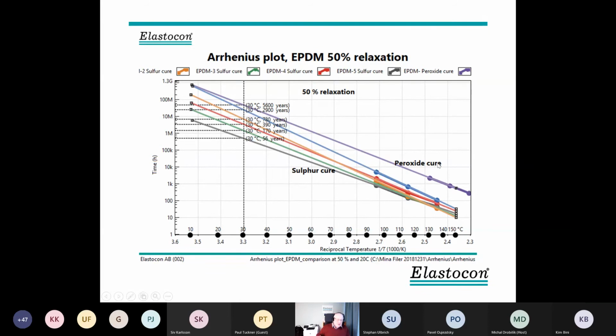I also added a peroxide cure. That was not a sealing ring compound. It was a compound for some other use, but it was an EPDM. And there we see that the peroxide is quite much better at high temperature, but at the lower temperatures, it's still the best, but not so much better. This is just a few of all the tests we've done on these kinds of materials. We have much more.